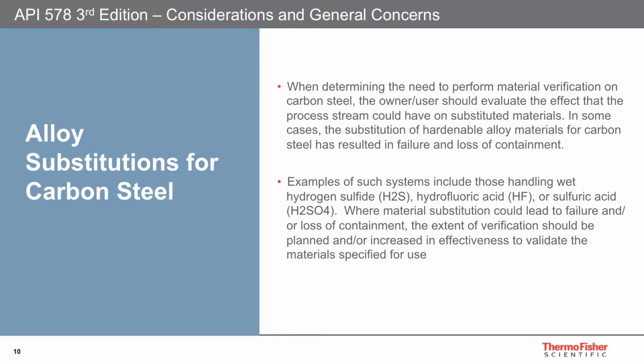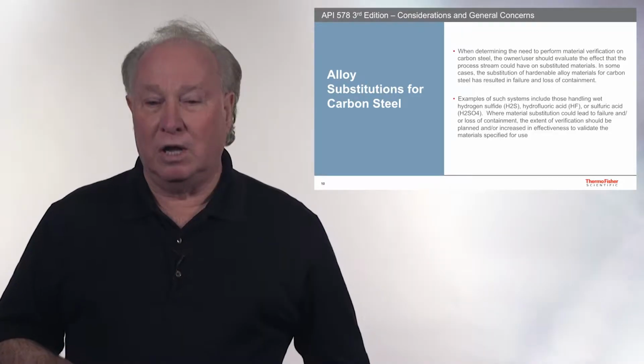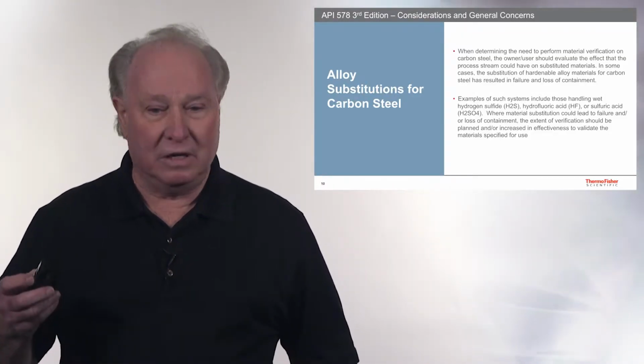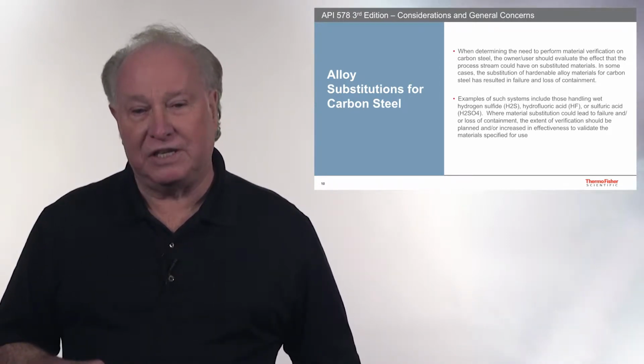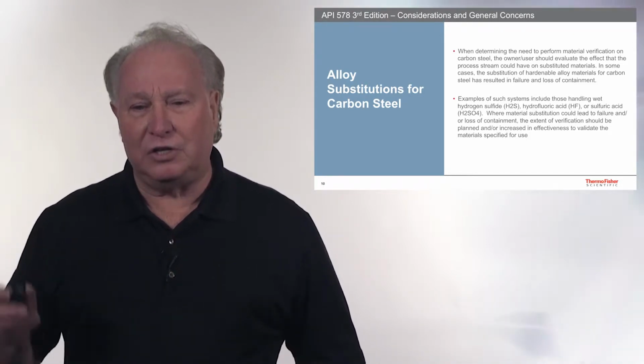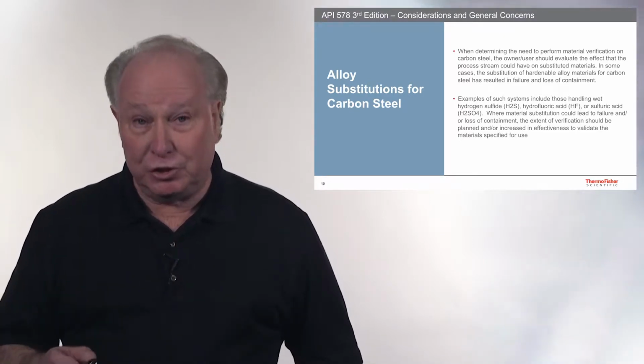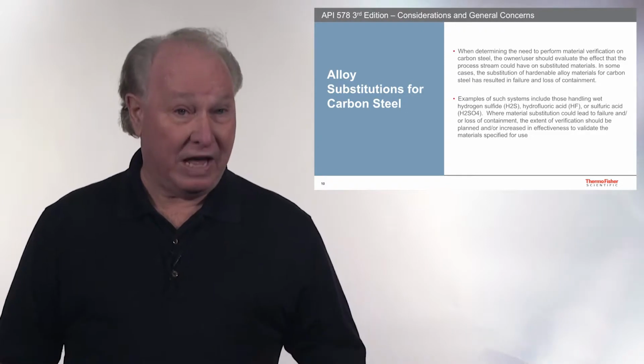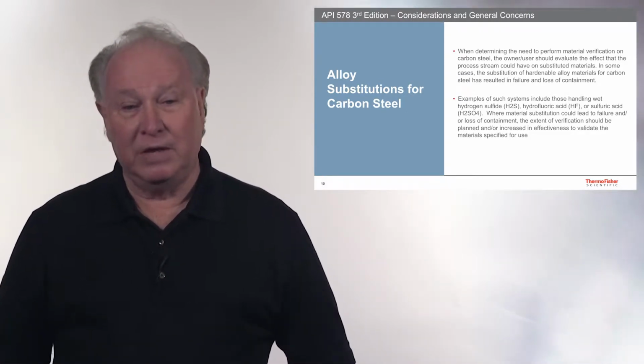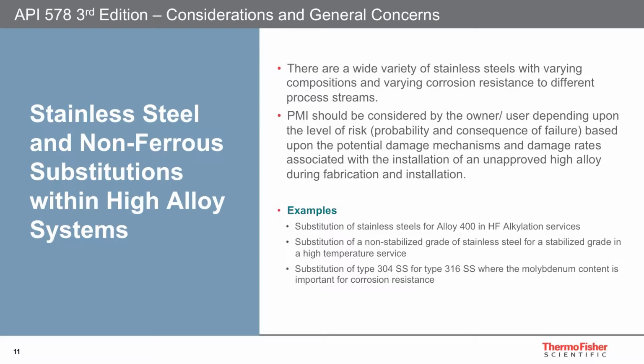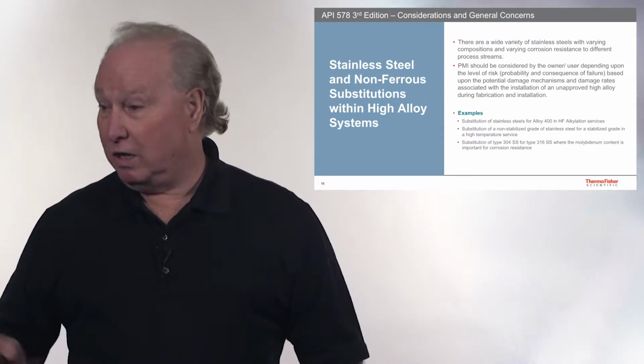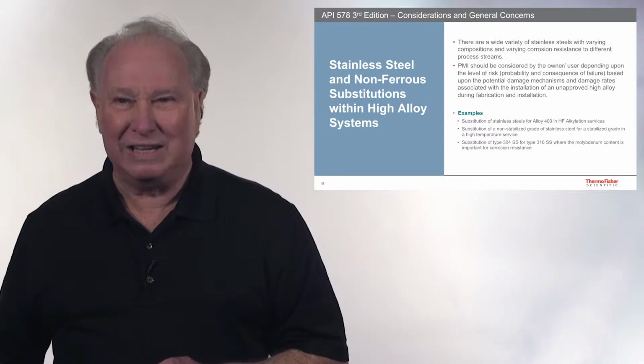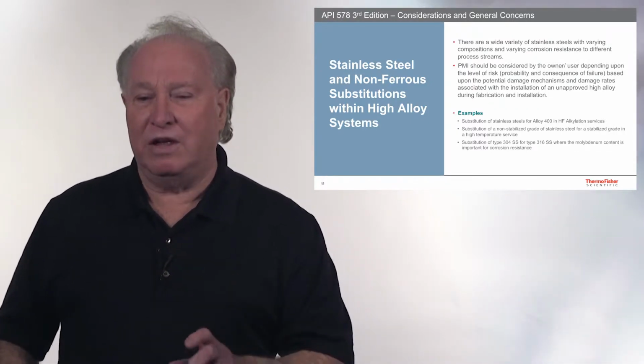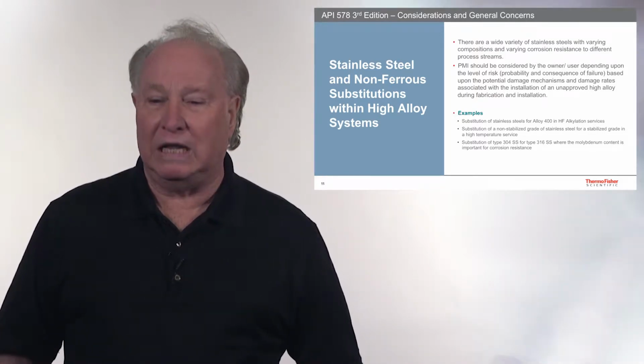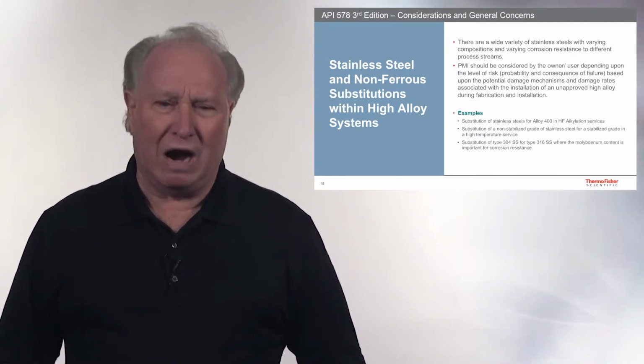The thing we talked about, considerations and concerns, is alloy substitutions in carbon steel. Where we have that HF acid, we have sulfuric acid, H2SO4, and anytime hydrogen sulfide's in there, you've got to really make sure you have the right substitutions of alloys in there and not just use carbon steel. So we mentioned that in the document. The other concern in this document is stainless steels and non-ferrous substitutions for high alloys. I use the word HF alkylation, so the alloy 400 has to be there. We have alloys like 304 stainless steel and 316, and 316 has molybdenum in it. We call it moly because molybdenum is very hard to say. So that has to be there, and if you don't test it and make sure 316 has the moly in it, then that can create a corrosion problem. So those are a wide variety of concerns.